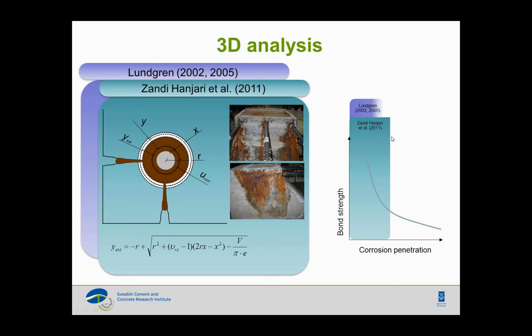What we do is that in each step of analysis we take out the stresses and the strains from Diana. We bring that into our MATLAB script, and we look into the crack width pattern and whether or not the cracks have joined together to develop a delamination plane. And if that is not the case, then we go back to the simulation and continue. But if that is the case, if we have large crack widths and we have formed a delamination plane, then we go to Diana.